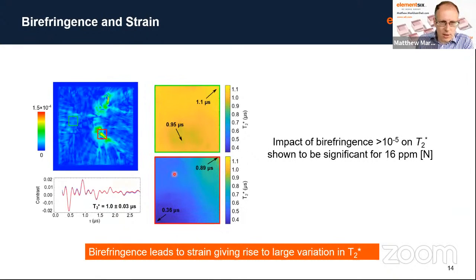So this little red window here corresponds to this plot here, and we can see that across that plot, the T2 star varies from 0.36 microseconds to 0.89 microseconds. So large variation across a small area, whereas if we take an area where the birefringence is more uniform, we see that the T2 star does not vary.